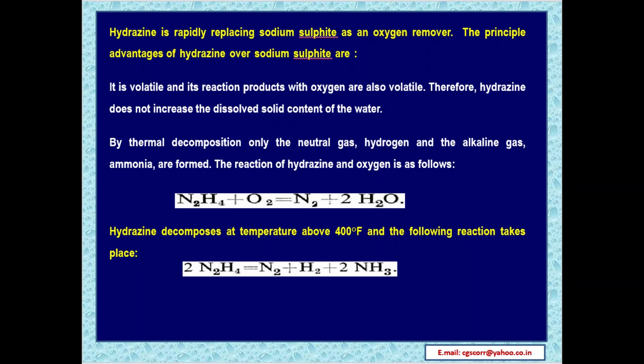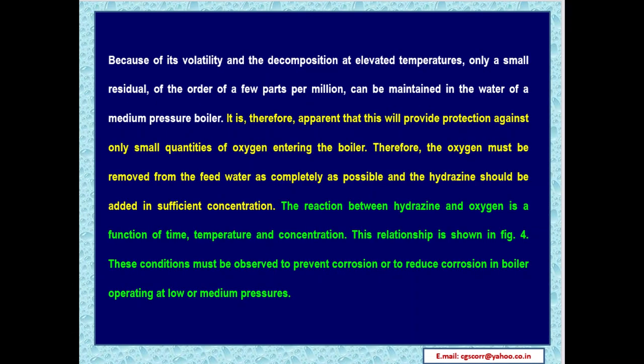By thermal decomposition, only the neutral gas, nitrogen, and alkaline gas, ammonia, are formed. The reaction of hydrazine and oxygen is as follows. Hydrazine N2H4 plus O2 gives you nitrogen plus H2O, water. Hydrazine decomposes at temperatures above 400 degrees Fahrenheit and the following reaction takes place. Hydrazine gives nitrogen and hydrogen and ammonia. Because of the volatility and the decomposition at elevated temperatures, only a small residual of the order of a few parts per million can be maintained in the water of a medium pressure boiler. It is therefore apparent that this will provide protection against only small quantities of oxygen entering the boiler.